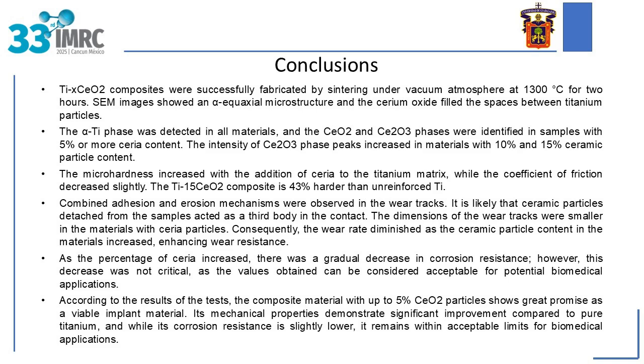The dimensions of the wear tracks were smaller in the materials with ceria particles. Consequently, the wear rate diminished as the particle content in the materials increased, enhancing wear resistance. As the percentage of ceria increased, there was a gradual decrease in corrosion resistance. However, this decrease was not critical, as the values obtained can be considered acceptable for potential biomedical applications.